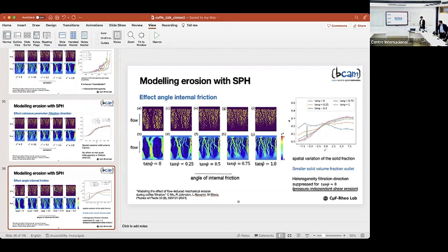I think that the explanation for the shear erosion, of course, is that there is a positive feedback mechanism between this random small channel that might occur in the porous media. In a small channel, we have less flow rate, the stress will be smaller, the flow will go to the larger one, and therefore it will increase the velocity and the stress. It will probably be that the fact that you erode also the bottom part might increase the overall velocity. In this case, for example, phi goes to zero, and therefore essentially it produces a large velocity over the entire transverse direction. This could act as a kind of homogenization, perhaps.